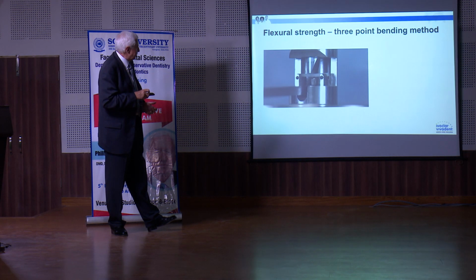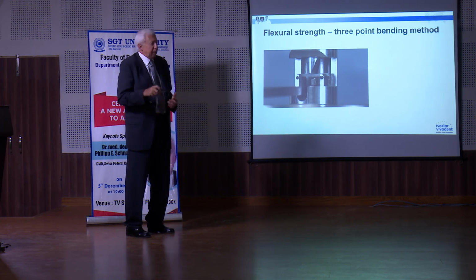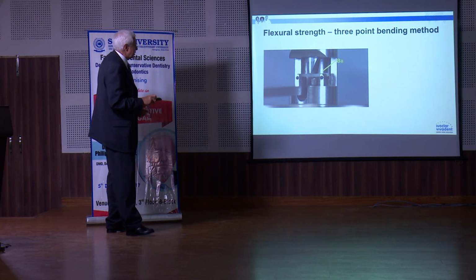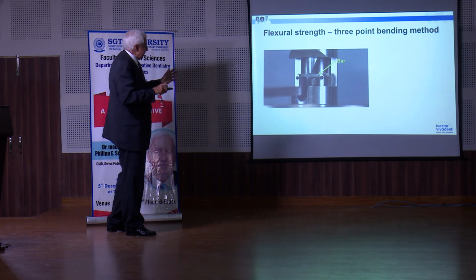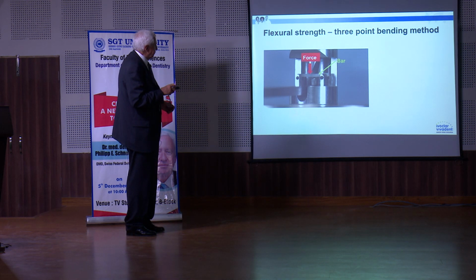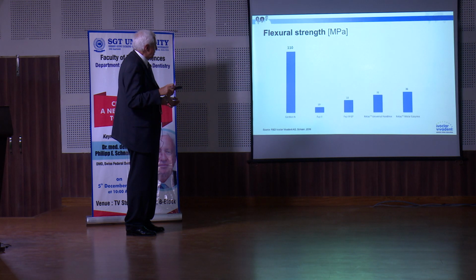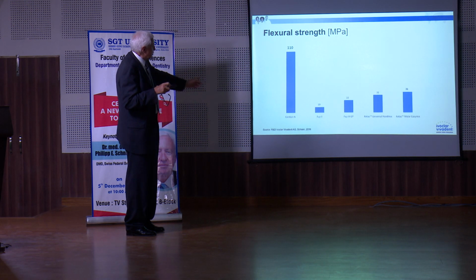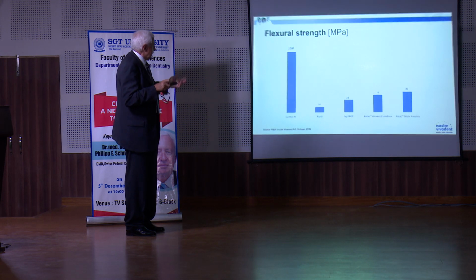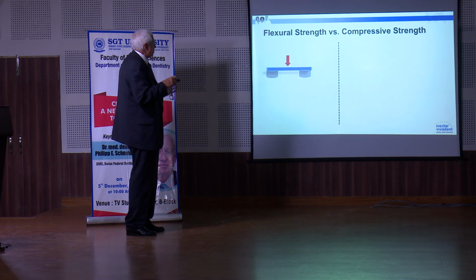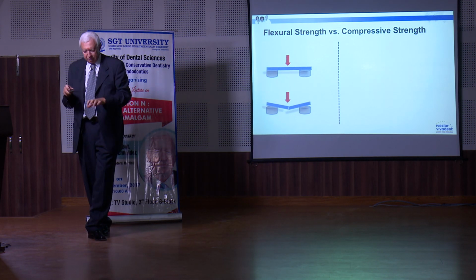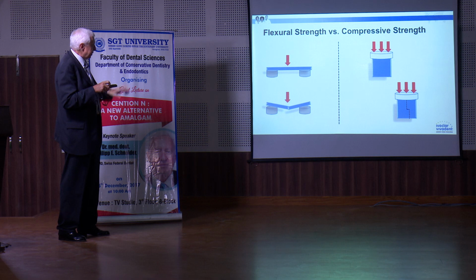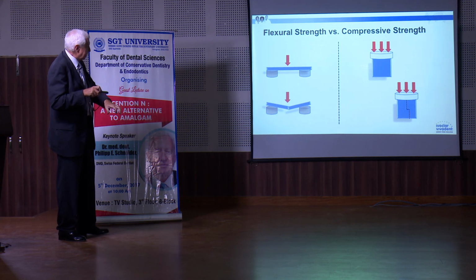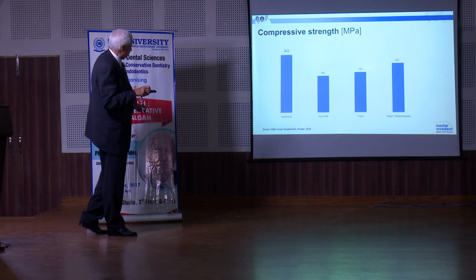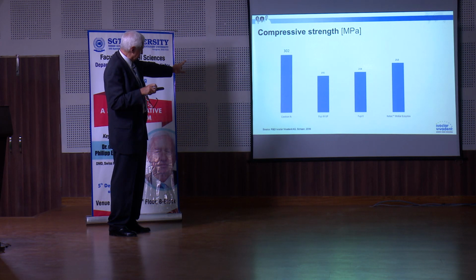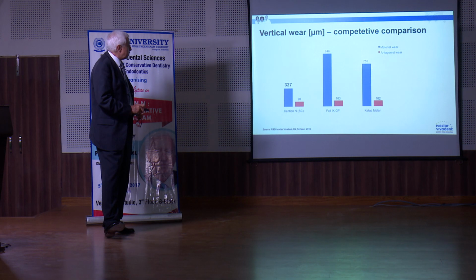In vitro results. We check the flexural strength. I told you we cannot measure this at the clinic in the patient. The idea is with this bar, you know, with the force, and then you see again much more than 100 compared to glass ionomer. Then, flexural strength versus compressive strength. That's another point. So this is the type of compressive strength, and you see also that we have wonderful data for Cention N compared to glass ionomer.